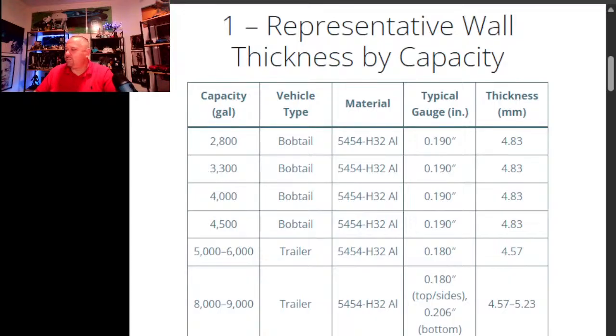With this being said, wall thickness on these aluminum tankers typically ranges between 4.6 and 5.3 millimeters, depending on size and position. Removing the metal, even in small amounts, can push the tanker below design minimum thickness, which can lead to non-compliance with DOT regulations and increased risk under pressure and impact.